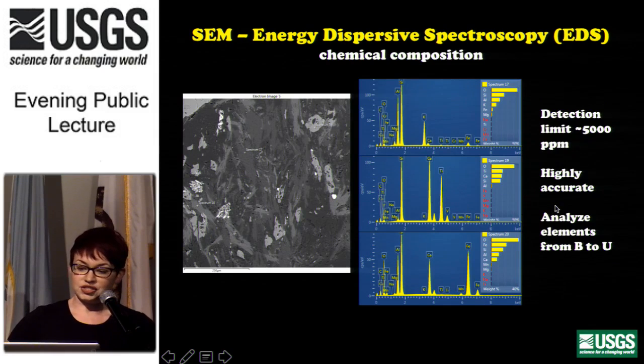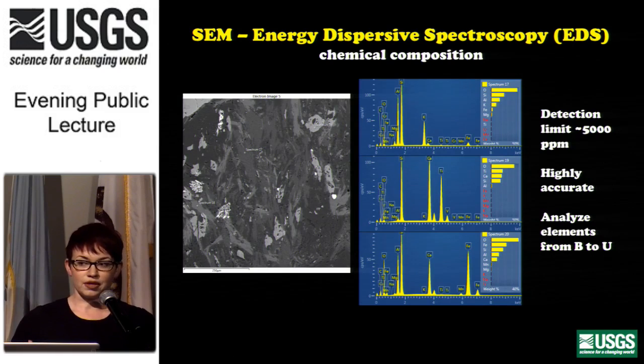The advantage of EDS is that it's highly accurate, especially the new systems and the new detectors, the modern instruments. It can analyze almost the entire periodic table, from boron to uranium. And if it has any limitations, it's that the detection limit is only about 3 to 5,000 parts per million. So it's not so good for trace elements, but it's really good if you have a rock and you just want to know what the minerals in this rock are. It's very quick.